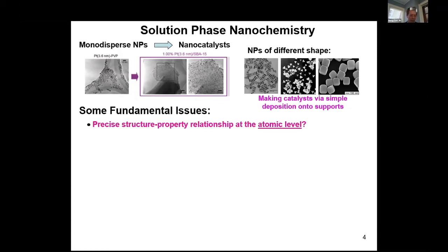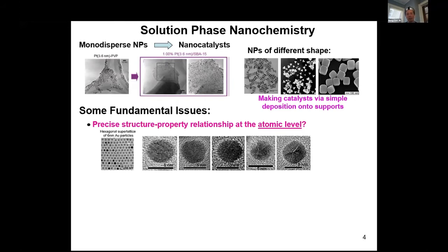But there are still some fundamental issues. So one is the precise structure-activity relationship at the atomic level. So for example, let me use these highly monodispersed nanoparticles with a 5 nanometer average size, right? So they're highly monodispersed. But if you look at them one by one on the high resolution TEM, they're not really the same. So for example, the first one is spherical, the second is polyhedral, and then we have a 5-fold twin particle as well. So at the low magnification in the TEM, they are highly monodispersed, almost the same. But if you look at them one by one, they're not really exactly the same. So for most purposes, yes, it's fine, it's not a big issue.